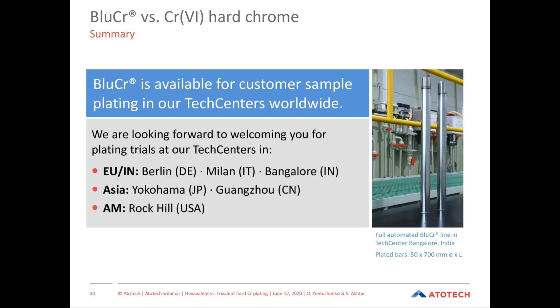Thank you. There's another question. What is the minimum thickness required to achieve sufficient corrosion protection? So maybe I can answer this question. To be honest, the thickness you require will be dependent very much on the type of application you are looking at. And for sure, we can advise for specific applications what the best thicknesses are for both the nickel layer and the blue chrome layer. But normally, as a standard, we say that you plate 10 microns of nickel and 20 microns of blue chrome to achieve 240 hours in neutral salt spray.